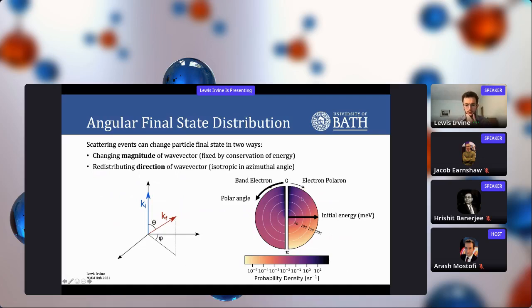So we came up with these plots here, which I should probably explain because it's a little bit complicated. It's a polar plot. Up here you have 0 angles, and it shows the probability density of scattering to a particular angle from 0 to pi as a function of the initial energy, which is the radial coordinate here, for band electrons on the left-hand side, and electron polarons on the right-hand side, so that we can compare them directly. The darker a color is, the more likely a particle is able to scatter into it from an initial angle of 0. As you can see for this example, it's very strongly forward scattering for both band electrons and electron polarons, because all of the probability density is clustered around here.